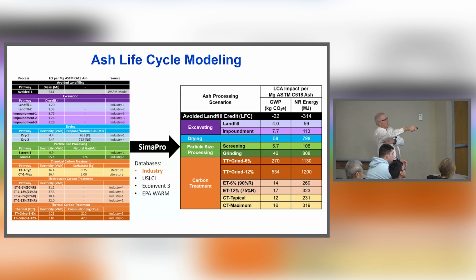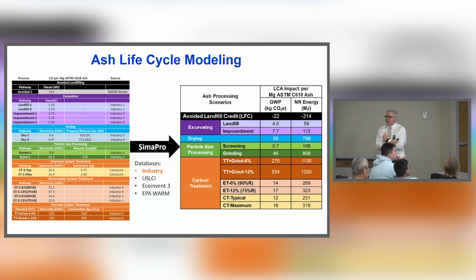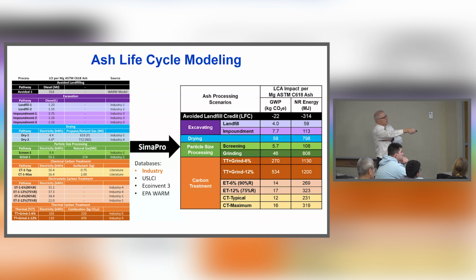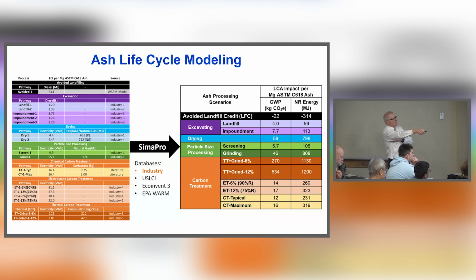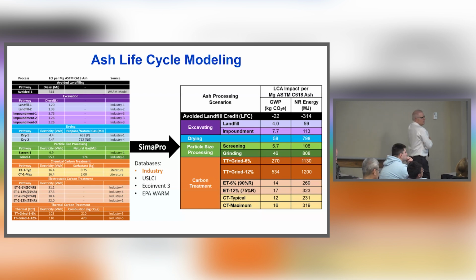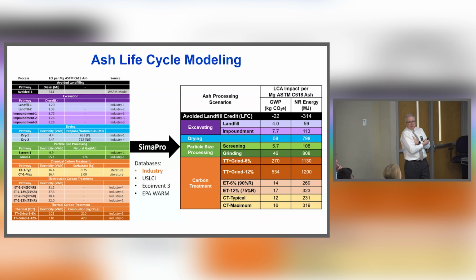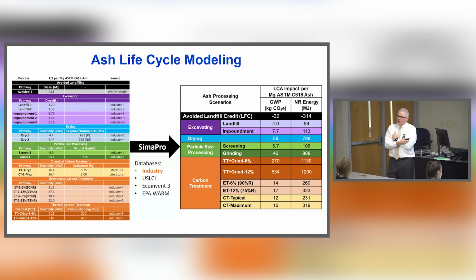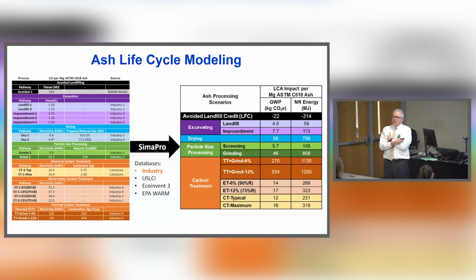So for example, we had it calculate the greenhouse gas emissions from excavating the ash, whether we were excavating it from a landfill or from an impoundment, and this is per ton of ash we're producing at the end, all right? Interestingly enough, excavating it from a landfill creates 4 kilograms of carbon dioxide equivalents, whereas from an impoundment, 7.7. Why would I generate more greenhouse gases from excavating it out of an impoundment than out of a dry landfill?